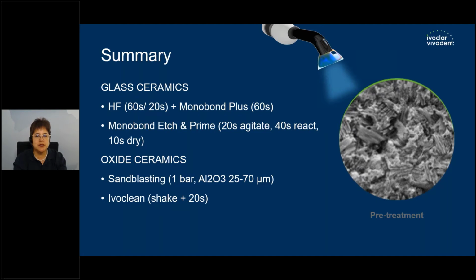To sum up the second chapter, I also want to put some light on the different points. We have different pre-treatment options. First, for glass ceramic, we have two options. The first option is using hydrofluoric acid, and depending on the glass phase, you leave the reaction for 60 seconds for feldspar or leucite reinforced glass ceramic, and for lithium disilicate, we have to etch for 20 seconds. Additionally, we need Monobond Plus for 60 seconds for silanization. The second option is to use Monobond Etch and Prime for the glass ceramic, where you have to agitate for 20 seconds, let it rest for 40 seconds, then rinse and dry for 10 seconds.